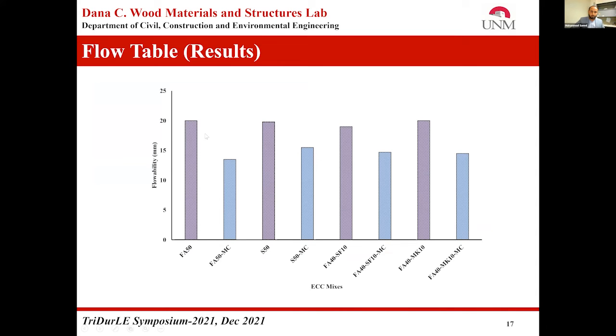The flow table results show that the mixes with the addition of viscosity modifying admixtures have significantly lower flowability, because methyl cellulose has a potential for water retention that leads to low flowability, and we need to adjust the water binder ratio of these mixes to make them printable.